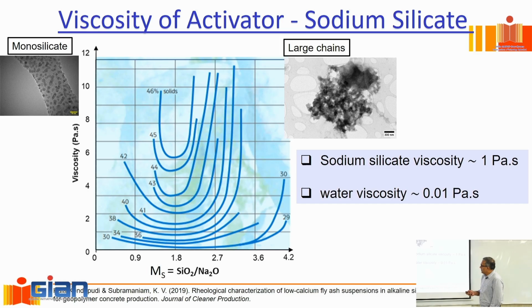Now, this is the viscosity of a solution for different silica contents. Each of these lines is for a different silica content. If I take a line like this, this has 46% by weight of the solution in dissolved silica. Whereas by the time you come down here, it has 30% of the total weight of the solution in dissolved silica. You may be wondering, why would I want to dissolve silica in a solution? Well, most commercial solutions, including paints, contain dissolved silica. It is typically used as a viscosity regulator in a lot of these applications, including some cough syrups. So what do I use silica for? For regulating the viscosity.